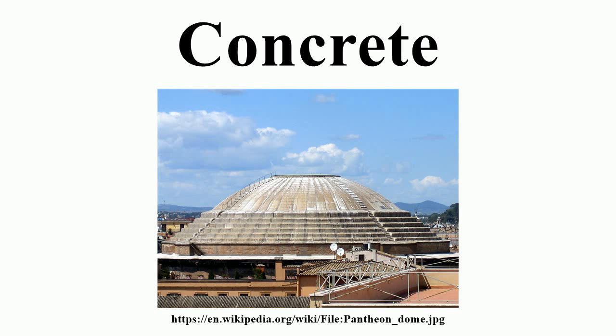Silica fume, a byproduct of the production of silicon and ferrosilicon alloys. Silica fume is similar to fly ash, but has a particle size 100 times smaller. This results in a higher surface-to-volume ratio and a much faster pozzolanic reaction. Silica fume is used to increase strength and durability of concrete, but generally requires the use of superplasticizers for workability.